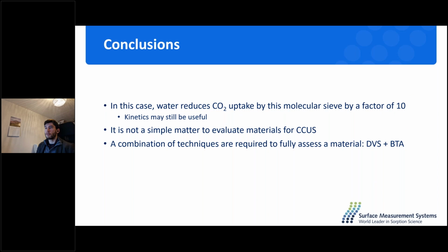So to conclude for this study, water does reduce CO2 uptake by about a factor of 10. We've pretty conclusively proved this by using both breakthrough analysis and gravimetry. One thing to note is that the kinetics of CO2 adsorption and the kinetics of water sorption are vastly different. CO2 appears much faster than water, which takes a lot longer. So perhaps not everything is lost. If we think about this material, maybe it can be used in a kinetics-based process rather than an equilibrium-based process to separate CO2 and water, to still use it in a carbon capture process.